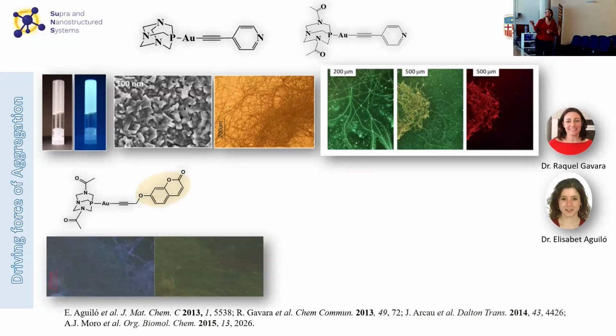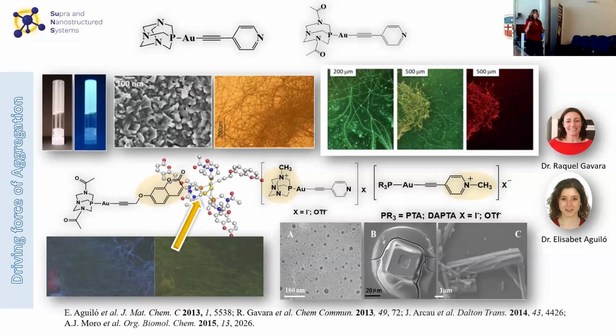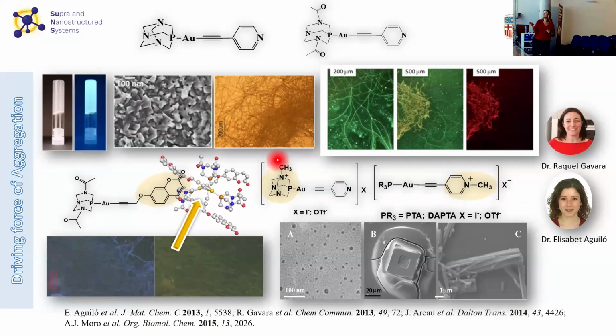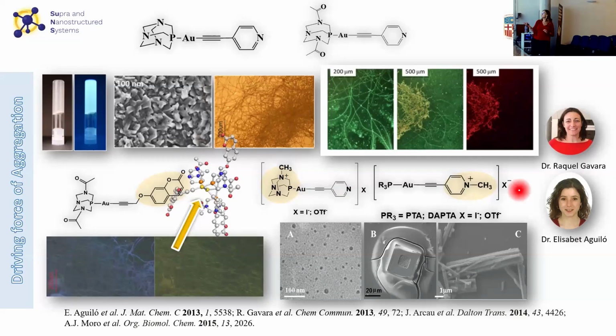But this is what happens, and it can also be extended, changing the chromophore. So instead of a pyridyl, you will have a coumarin. It happens the same. We have these very long fibers, but we can make other modifications, not only modifying the chromophore, but we can also introduce positive or negative charges in the molecule. In these cases, we could confirm the presence of aurophilic interactions thanks to the X-ray crystal structure. As I said, if we introduce a positive charge in the molecule, what we observe is a radical change in the supramolecular assemblies. So we can introduce a positive charge here, at this nitrogen atom of the phosphane, or at the nitrogen atom of the pyridyl group.